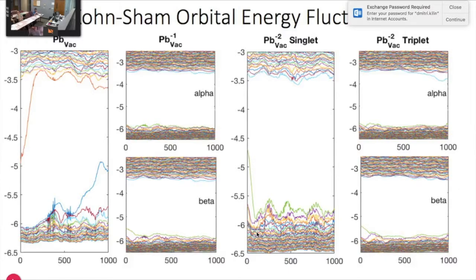So going from the ground state to the heating molecular dynamics, trying to provide updated coordinates in some ambient room temperature condition that would resemble experiment, what we're able to do is look at how the electronic energies of each Kohn-Sham orbital change as the atomic positions are updated according to this dynamic trajectory. What's shown on the screen here are 4 different trajectories. On the very left, there are the energy fluctuations for the lead vacancy with no charge. And then secondly, there are the spin up and spin down fluctuations for the lead vacancy with 1 charge.